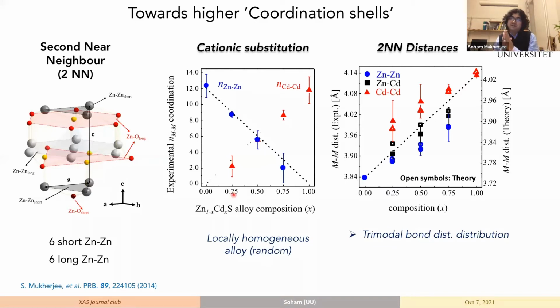When you look at the second near neighbor distances, we immediately see that there are three different kinds of distances, which is not very surprising in the sense that we now have a mixture of two atoms. If you do a 3C2, you will get three different kinds of combinations, and this is exactly what it is. We see that the cadmium-cadmium distances are still longer, and zinc-zinc distances are shorter than the average line, which is the virtual crystal line. And zinc to cadmium distances lie somewhere in between.